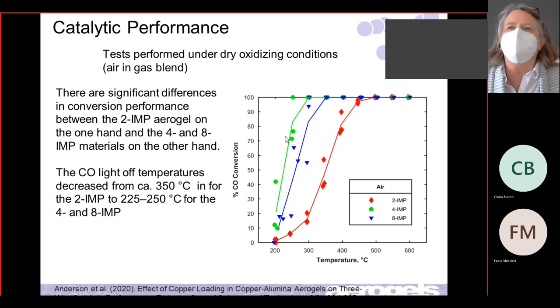So this is showing us that, oh okay, adding more than 2 was good, adding 4 was good, 8 was marginally better. Going to 16 probably isn't really going to help. But what's nice is you see we do a pretty good job with these materials of converting the CO at low temperatures. I should tell you the goal is to get below 200. Well, we're not that far. So these are not optimized, we just made them and tried them.